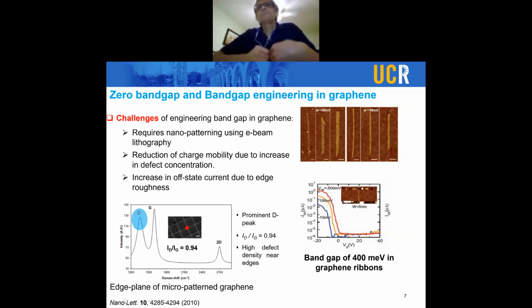Some others decided to start band gap engineering, and we also tried a couple of different methods. One is to make nanoribbons. Instead of making nanoribbons, we started to make nanomesh, so that we were going to look at a much bigger surface as opposed to thin strips of nanoribbons. Secondly, is to introduce defects to introduce a band gap. But when you introduce defects, you lose the conductivity of the material, the charge mobility, and other properties. So even though you do introduce a band gap by doing this band gap engineering, unfortunately, it's not the right approach to take.